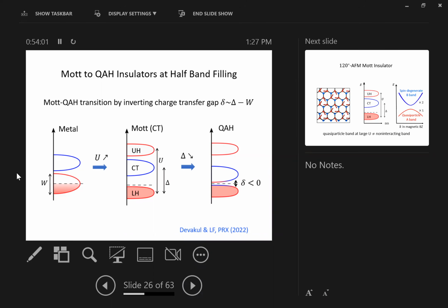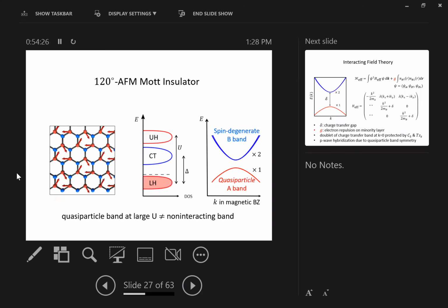Okay, so this is very much like the previous band inversion picture, but the difference is that first, we're not starting from the non-interacting band structure anymore. Our starting point is this lower Hubbard band, which is formed through strong interactions. And second, we will see that the band inversion between the lower Hubbard band and the charge transfer band is highly non-trivial. It's something beyond this free Dirac theory.